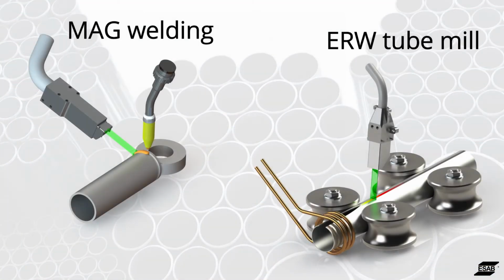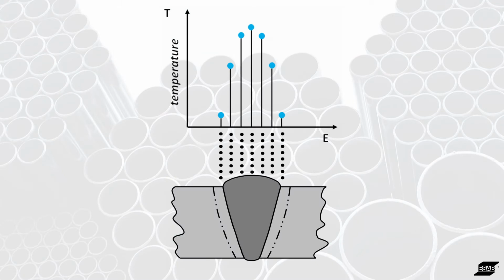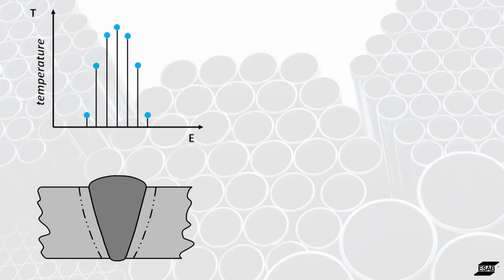The TPS measuring head captures, shortly behind the welding point, the temperature from the solidified weld seam. Depending on the welding process, the distance is just a few millimeters or a couple of centimeters. The measurement takes place across the seam and the heat affected zone. Each measurement captures the temperature distribution across the weld seam.